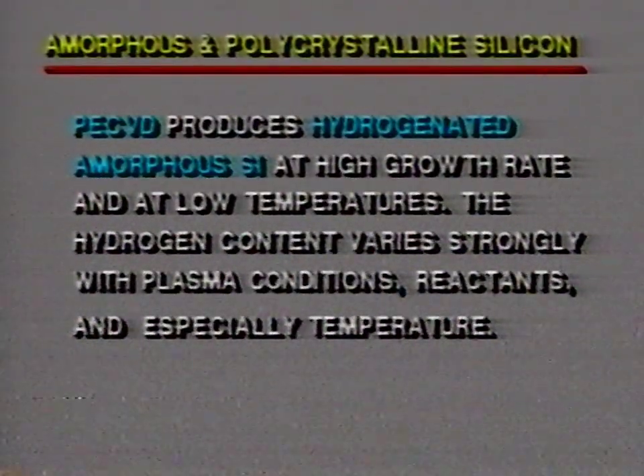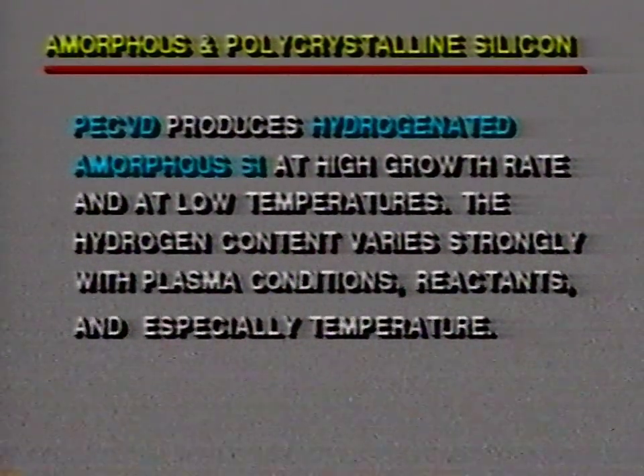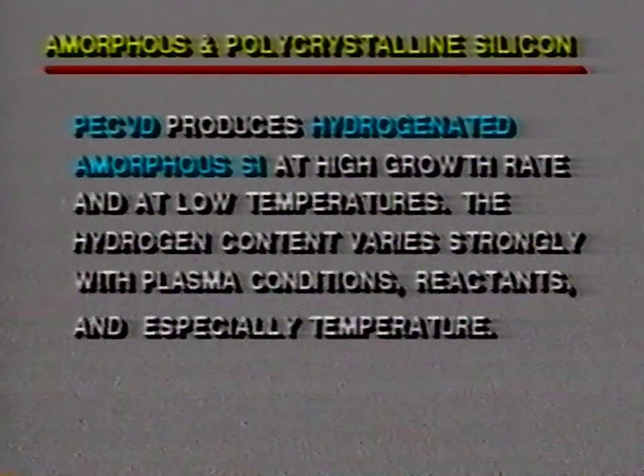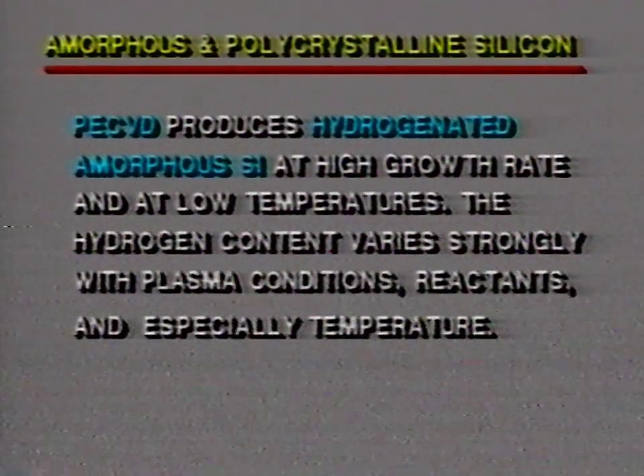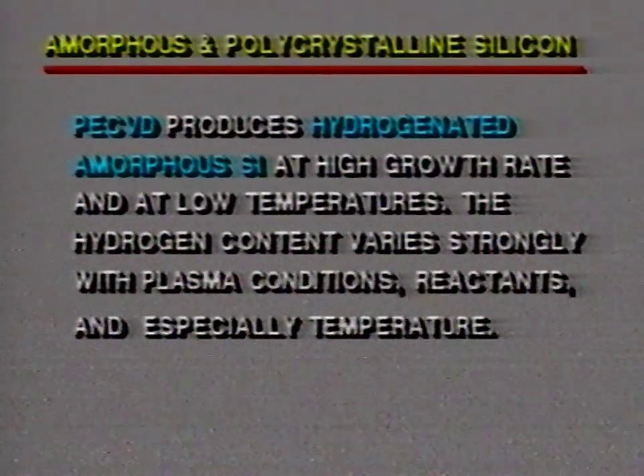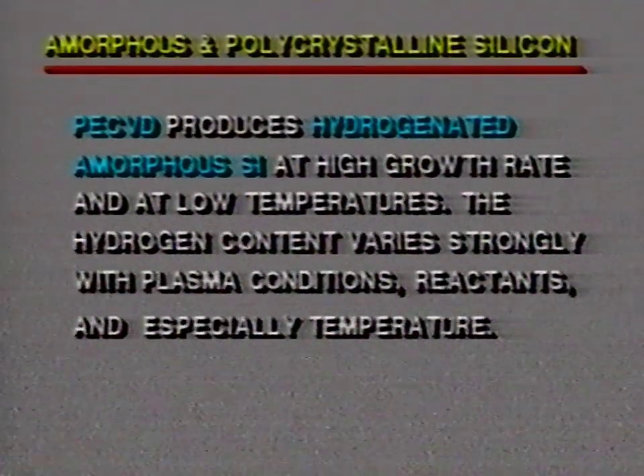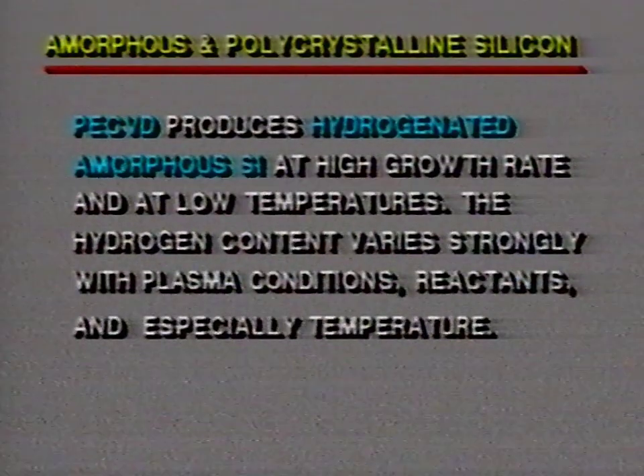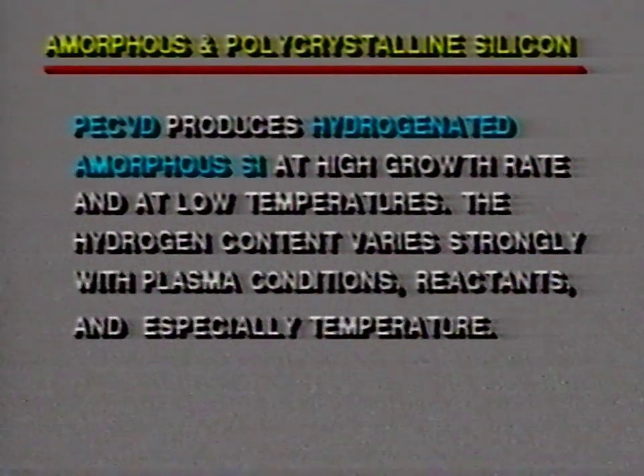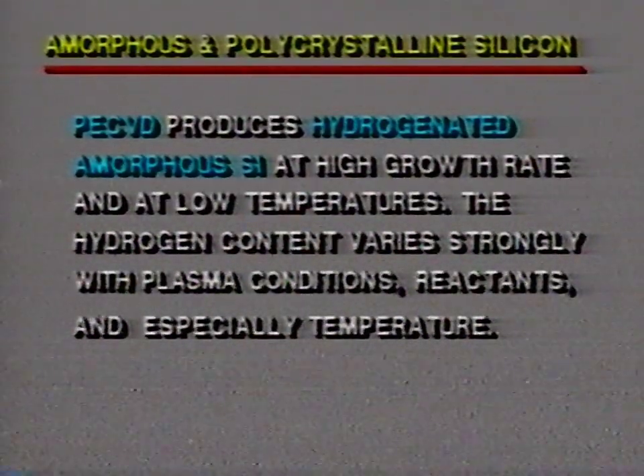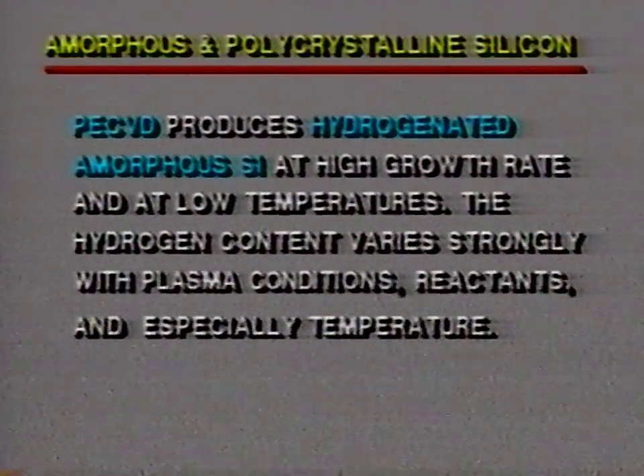Now the plasma-enhanced CVD or plasma-assisted type of CVD for silicon deposition will produce a hydrogenated amorphous silicon, which is produced at fairly high rates and at low temperatures. In this case, the hydrogen contents vary strongly with plasma conditions, reactants, and other factors, but especially the temperature. Again, as the temperature increases, there is less hydrogen being included. Of course, this type of film is used for photovoltaic applications primarily, where the hydrogen is, as an exception now, a beneficial effect. Namely, it will passivate dangling bonds and so on, and produce very desirable effects in solar cell applications, for example, where plasma amorphous silicon is used very widely.